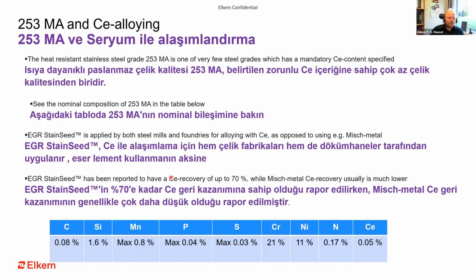Then we have the grade 253 MA. And the heat-resistant stainless grade 253 MA is one of very few steel grades which actually has a mandatory cerium content. And you see the composition here. It is a grade that was invented by Outokumpu Avesta many years ago. And it's probably the heat-resistant grade that can handle the highest service temperature, I think it's around 1150 degrees C, and is also very good for cycling between low and high temperatures. So, what you see here, the nominal composition is 500 ppm of cerium.